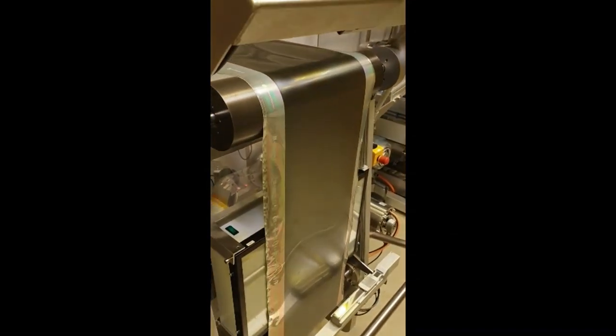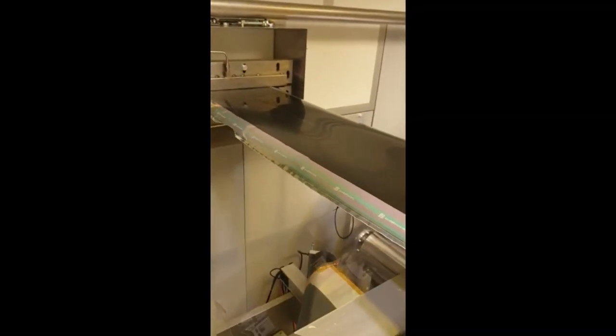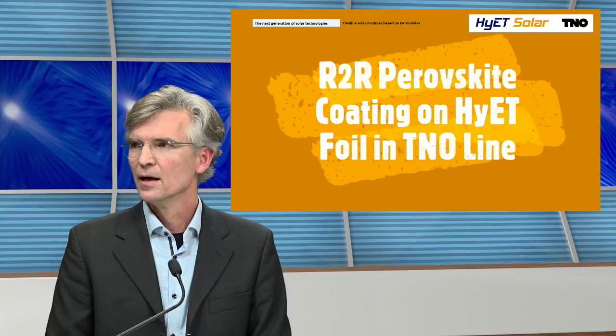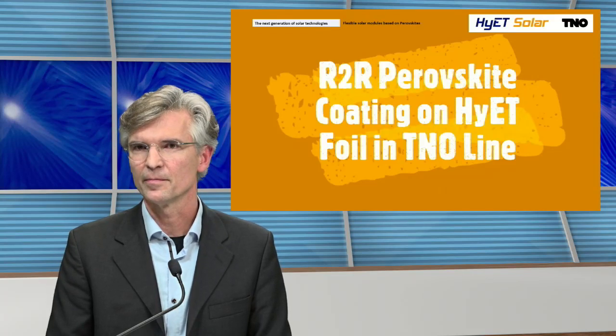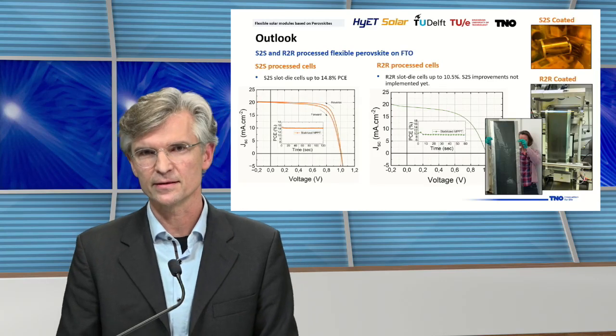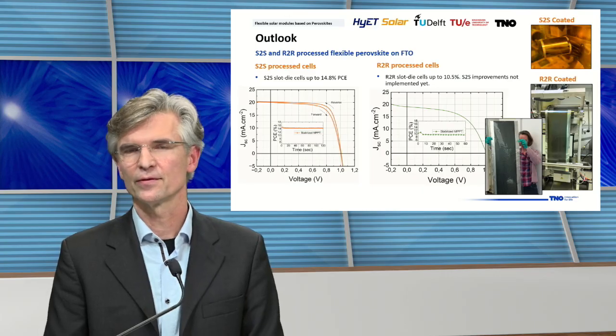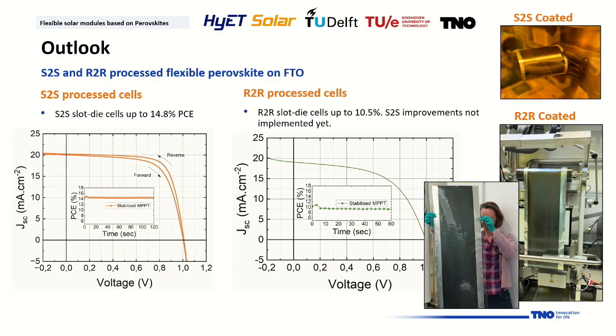So this we do together with our industrial partner, Hyet Solar. And the substrate that we use here is also what they use for commercial production of amorphous thin film solar. Now, if we look at the device performances that we can get, on the right-hand side, you see the IV curve that we can measure for the first roll-to-roll processed devices. And initial performance was 10.5% for these devices in the first batch. And then we further worked on these type of devices on sheet-to-sheet, and now we can achieve efficiencies of 14.8% together with Hyet Solar and in collaboration with Delft University and Eindhoven University.